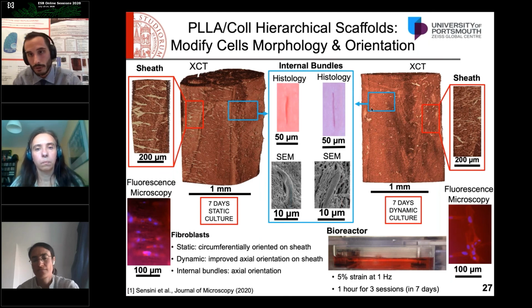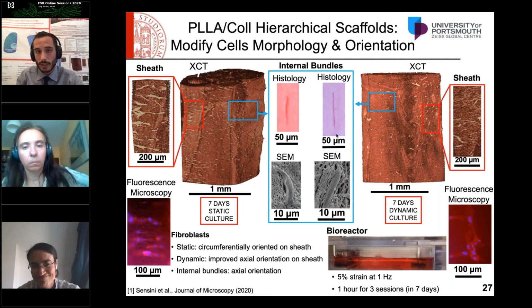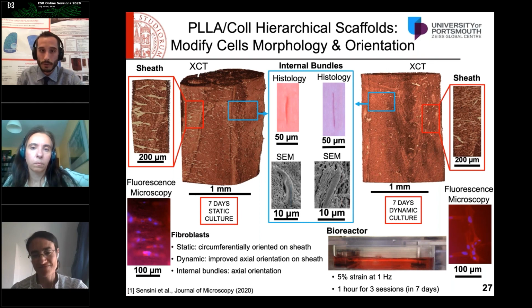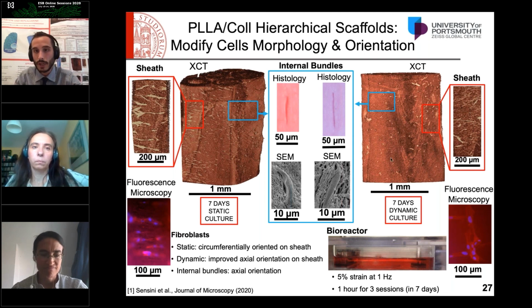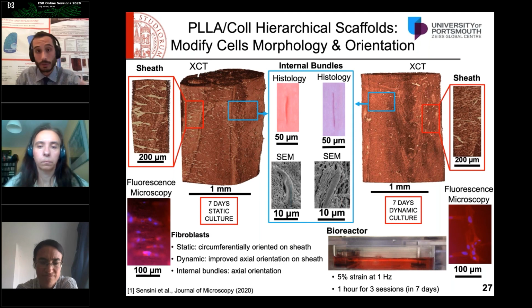Okay, for reason of time, maybe it was not really clear. But you can see that the cells are able to infiltrate inside the scaffolds and grow on the aligned bundles, aligned nanofibers inside. So basically they are able to infiltrate easily inside the porosity of the membrane, the micrometric porosities of the membranes, and grow throughout the whole structure of our scaffolds.